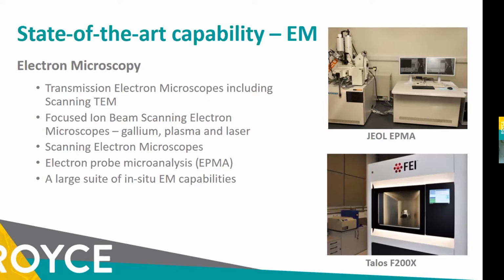We've also just had a high throughput large area EBSD system, and that allows us to study a large number of samples, but over very large areas. That's really great for characterizing long range texture studies and investigating large numbers of, say, additive manufacturing test builds and failure analysis samples as well.